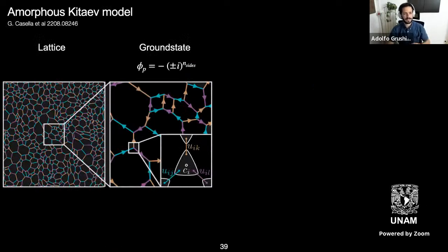What's a recent development is that Johannes Knolle's group in Munich generalized this to an amorphous lattice, which is quite interesting, though maybe not surprising, given that in the amorphous lattice you have all types of plaquettes, in particular odd-sided plaquettes. And so you break time reversal symmetry. You can still color the lattice with plus and minus, and find the flux configuration that minimizes the energy. This is the nice thing of this paper: they found the ground state flux configuration that minimizes the energy. This you have to do numerically.